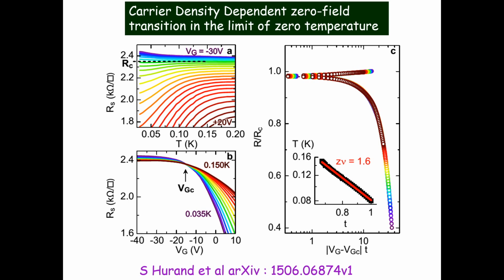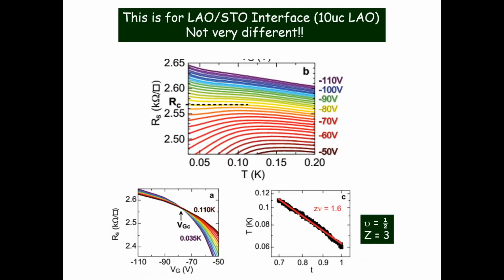Now, how different is this from the LAO-STO interface? There also you have superconductivity, and it turns out that there is hardly any difference between the two systems. Actually, we have done a very careful comparison between LTO-STO and LAO-STO. We see similar signatures in photoconductivity. We see similar signatures in the Hall effect and other things. So, in my opinion, these two materials are not actually very different. All the action is in the strontium titanate, just below whatever you put on the top.